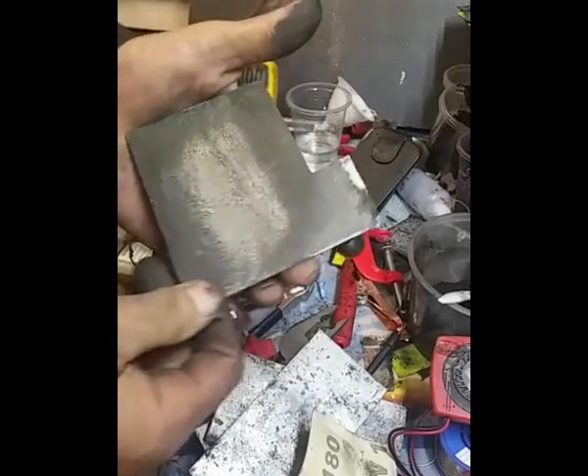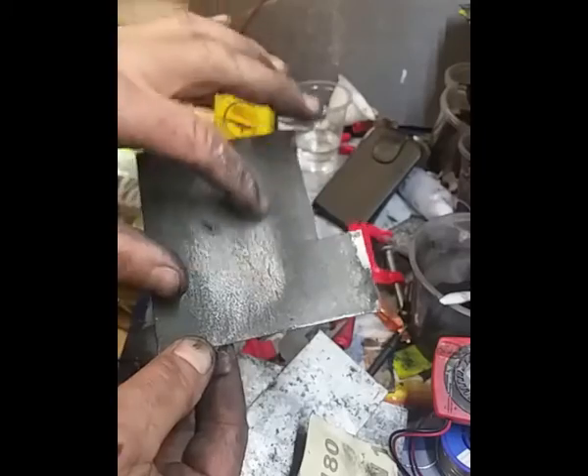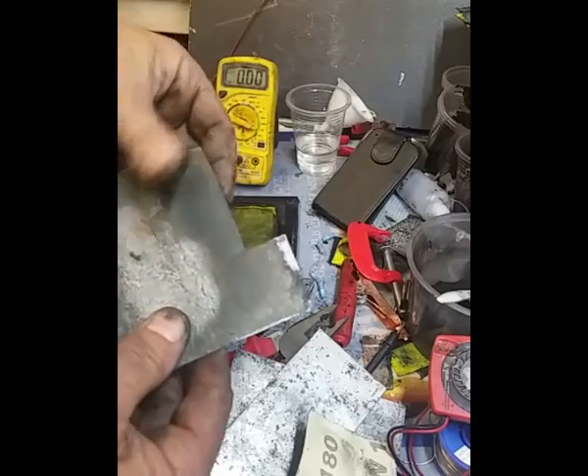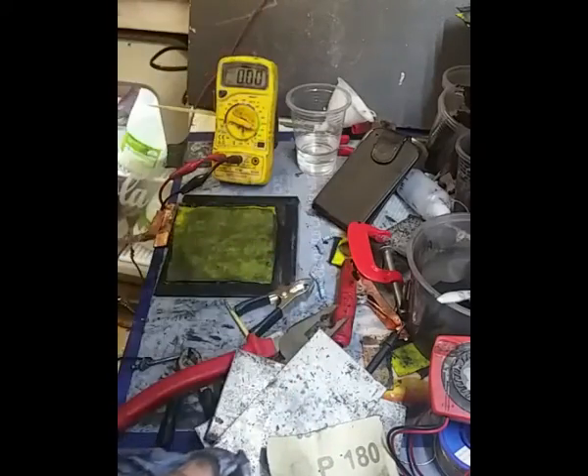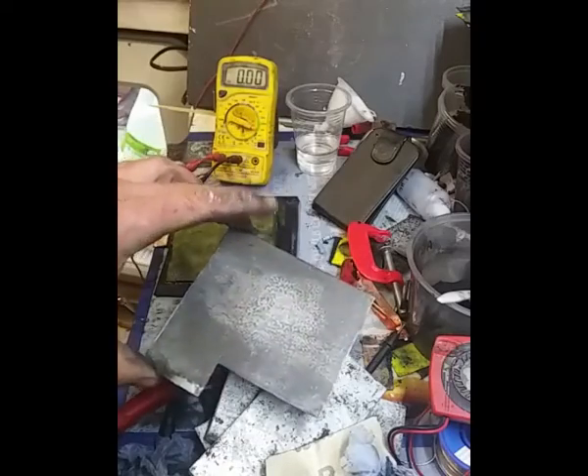There's been some degradation on the surface which I definitely wasn't getting when I put the hydroxide coating on there — it's definitely the way forward. I'll need to do a bit more research, read some more papers. Of all these metals, magnesium is probably one of the toughest to deal with, one of the hardest materials to use because of this sort of stuff.